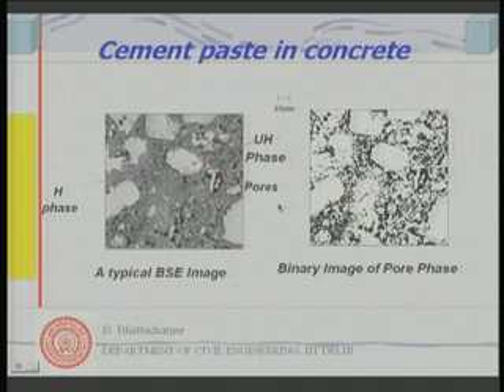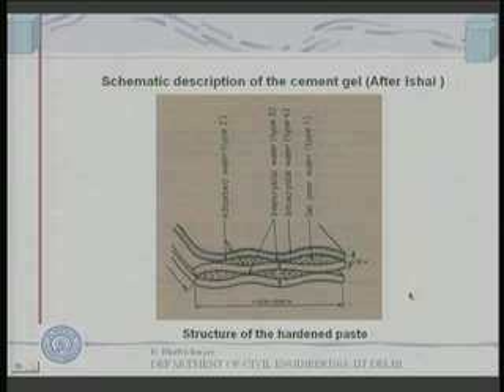It will depend, of course, on the ratio of water to cement and the degree of hydration, and 10 micron is the scale. So, that is what cement paste looks like. Now, people have tried to model this by various types of analytical experiments. People found that the structure of the CSH is fiber-like and gelatinous, and that was established as early as the 1950s by various people who studied it through scanning electron microscopy. People have also studied through nitrogen adsorption techniques the thickness of the interstitial layers and the gaps between them, and they found that it has a gelatinous structure.